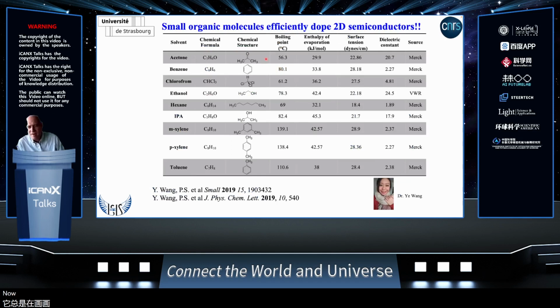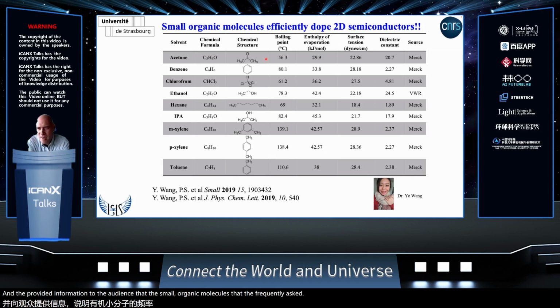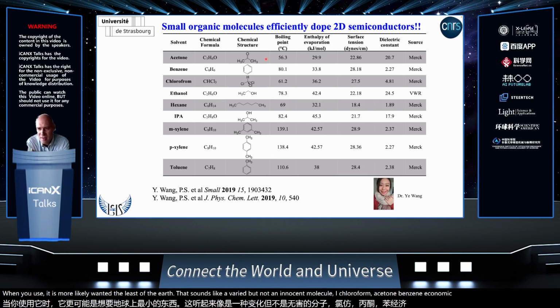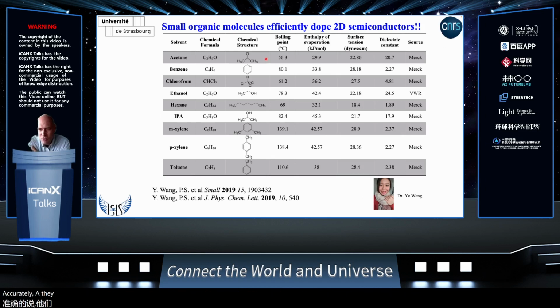Now, here I would like to open a very small window and provide the information to the audience that small organic molecules that are frequently used as solvent molecules, and so are supposed to be inert from the electronic point of view, are not really inert. So I warn you to watch out when you use a small molecule like the ones listed here, which sound like very banal and innocent molecules, like chloroform, acetone, benzene, ethanol, hexane. Actually, they do dope the semiconductor to a certain extent.